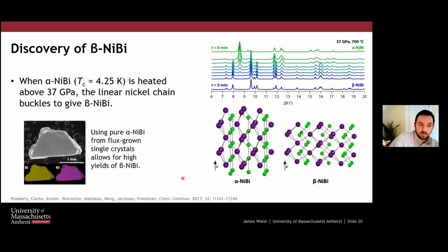So another system, nickel bismuth. So we know that nickel bismuth already has compounds under ambient conditions, but is there anything that we can discover in the phase space opened up by pressure? It turns out there is. So this is an interesting example of now taking, rather than a mixture of powders, a single crystal of an intermetallic, and you can see the hexagonal facets on this. This is a hexagonal system. This is a single crystal, really beautiful, which we then crushed and put into a diamond cell, but it's pure nickel bismuth. And so what we find is that when we heat above 37 GPa, we see this phase transition.